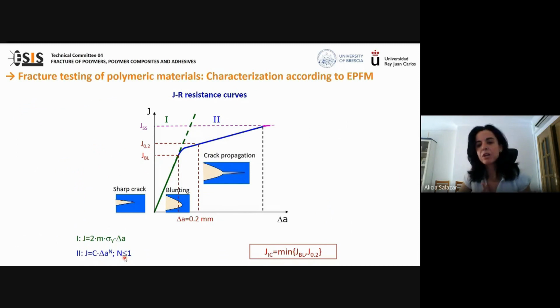In this slide, I want to describe briefly the JR curve. This curve displays the J integral values, which we'll see later how to calculate, versus the crack growth extension, delta a. Two regions are distinguished. Region 1, in green: the crack remains stationary, but crack tip blunting occurs. The crack growth due to blunting is described by a blunting line given by this expression, where M is a constraint factor which can have values between 1 and 3, and sigma Y is the yield strength. In region 2, in blue, real crack growth occurs, and the crack growth is described by a power law with an exponent n less than or equal to 1.